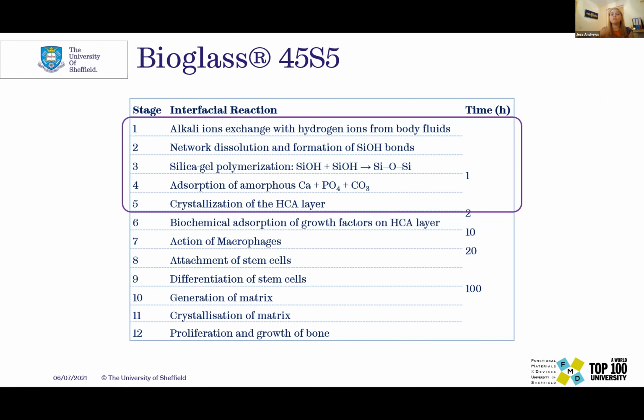When you implant bioglass into the body, there are a number of processes that it goes through, and the first 5 are really important to understanding the mechanism behind why and how bioglass cold sinters. So you get some alkali ion exchange, network dissolution, and repolymerization, and then you also get the beginnings of a crystallization of a hydroxyapatite layer.